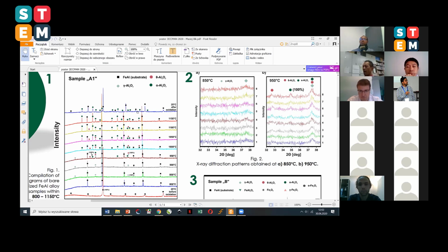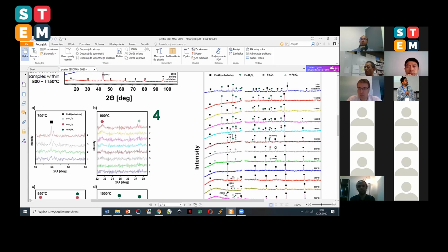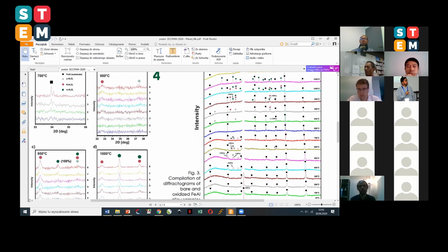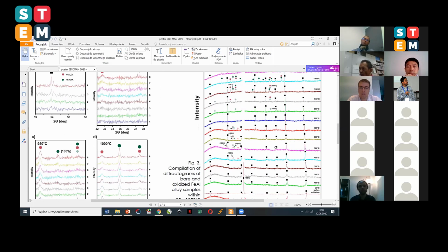And afterwards, at 1100, we observed a complete theta to alpha final phase transition of the alumina. And in the second part, we investigated also the lower temperature range. Why? Because in the literature we saw plenty of information concerning the formation of iron oxides or iron mixed oxides.